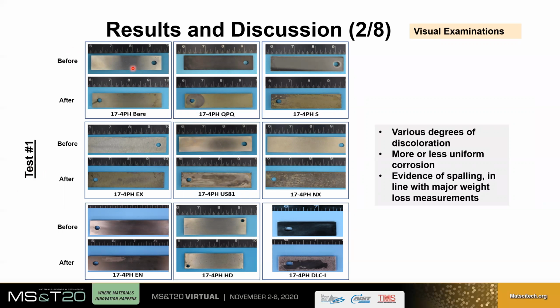So what we see is a discoloration in most cases. In fact, this discoloration tends to be on the golden side. Essentially, the exposure to H2S tends to discolor many of the coupons and make them a little bit more golden in appearance, which is actually extremely true for QPQ, a lot more than some other coatings. In some cases, it's very blackish, very, very black, which is an indication of more corrosion.